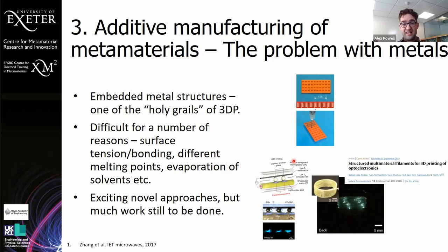Another way to do it is to try and inject inks, which is what Zhang et al. had done in Loughborough a few years ago. And even that's difficult because you have to evaporate your solvent to get good conductivity and reduce your loss in the metals. And then you have to sinter it if it's a nanoparticle ink. And again, the sintering temperature is often quite similar to melting temperatures of plastics. And you have to have a kind of structure that will allow your ink to evaporate. Otherwise, you'll get very high losses in your metals. So it's tricky. There's a lot to be done.